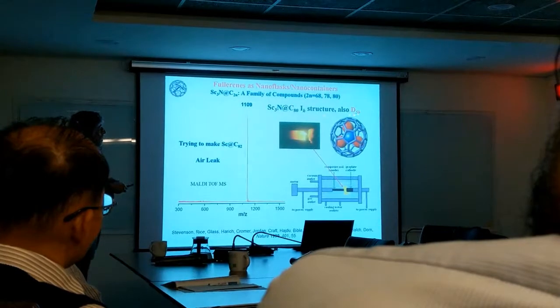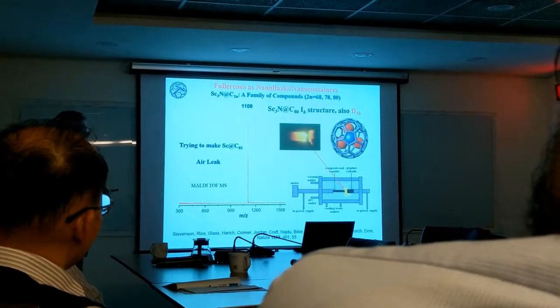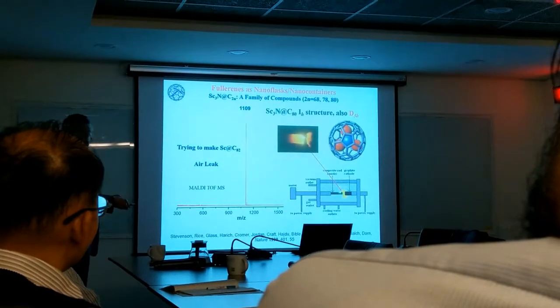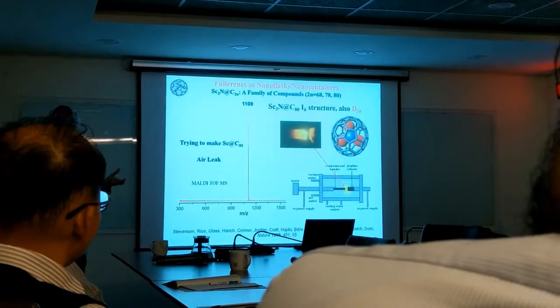atom, inside either icosahedral or D5h symmetry C80 cages. Okay? This is the crystal structure. Beautiful thing, by the way. The way you discharge this, you apply high current. The high current vaporizes the graphite with the scandium oxide, and you end up producing a plasma. And these compounds are formed within the plasma.